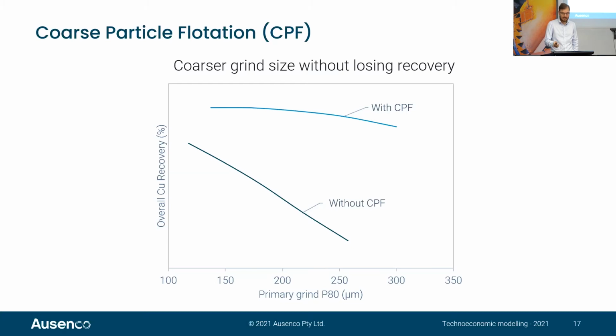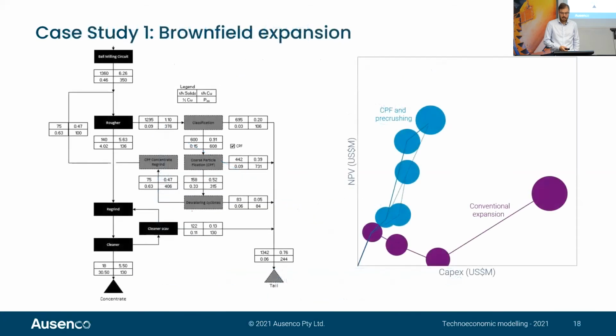So that kind of highlights the benefit from a technical perspective. And now if I go through a couple of case studies, this first case study was a Brownfields expansion where we were comparing coarse particle flotation, and it included pre-crushing to be able to debottleneck the SAG mill and allow the ball mill to grind coarser.